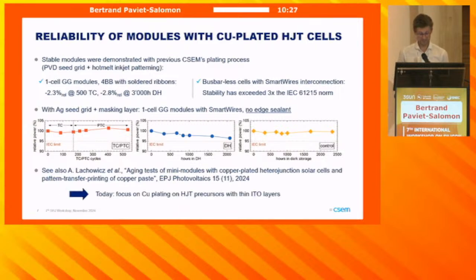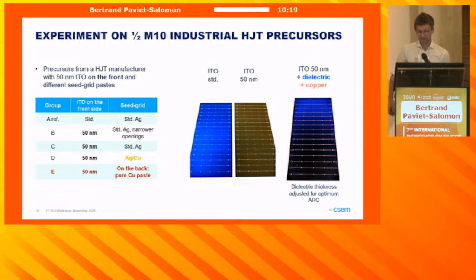So this being said, for today, I'd like to focus on recent results we obtained on heterojunction precursors with thin ITO layers. So let's get started. For those tests, we relied on M10 industrial precursors obtained from a manufacturer with whom we are in collaboration. They feature 50 nanometer thick ITO on the front, and then we applied different seed grids on them. We range from standard silver paste with standard openings. We tested obviously some silver-coated copper paste and even advanced splits with pure copper paste on the back.